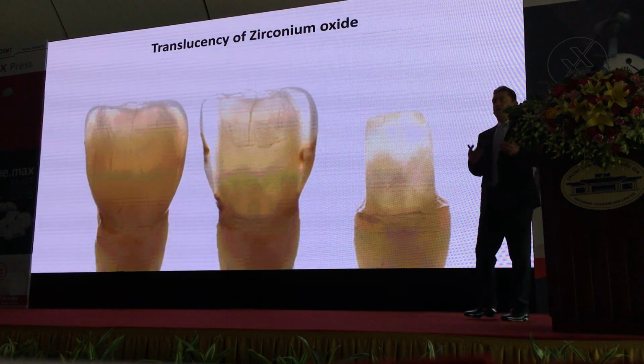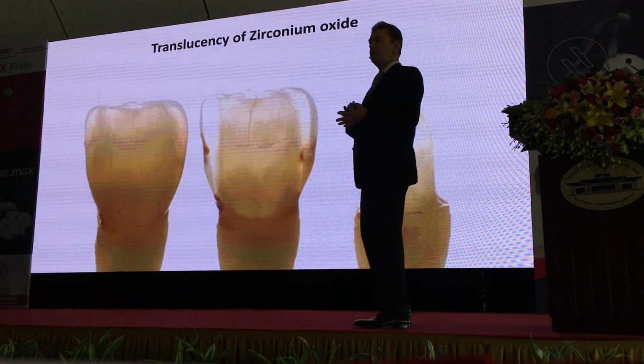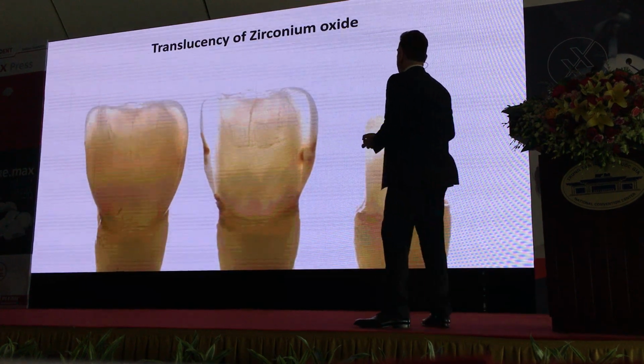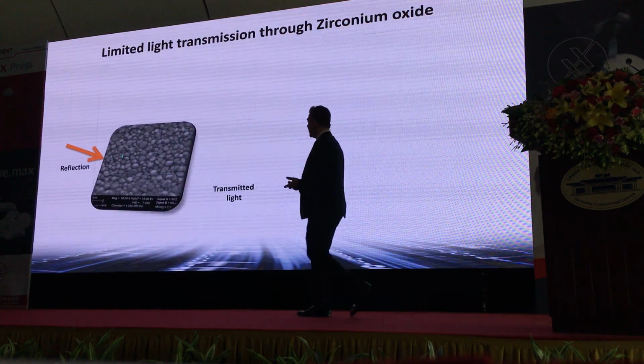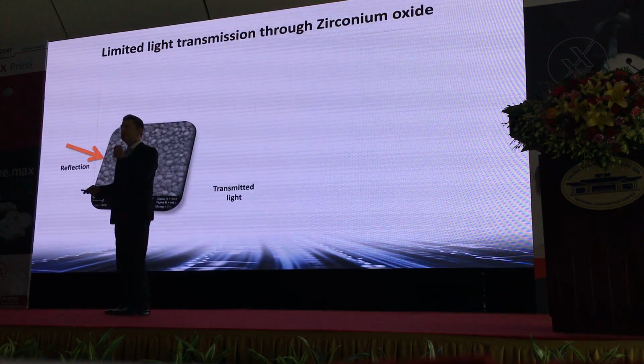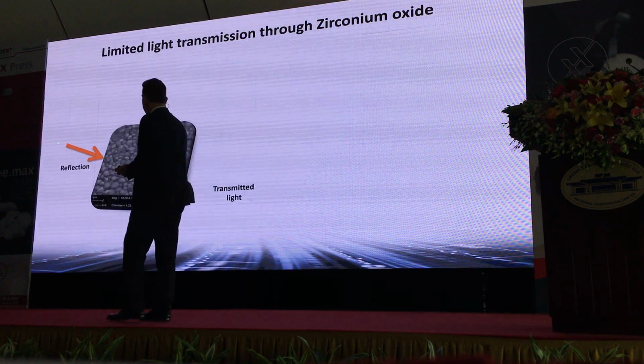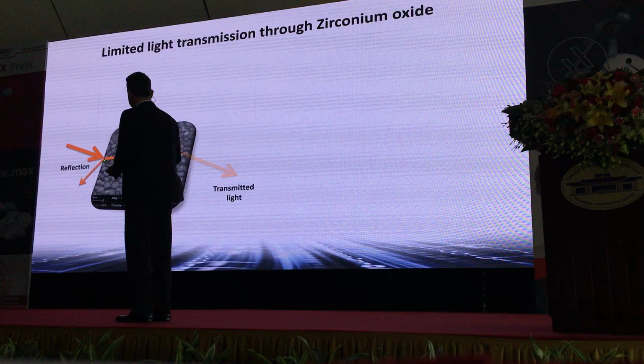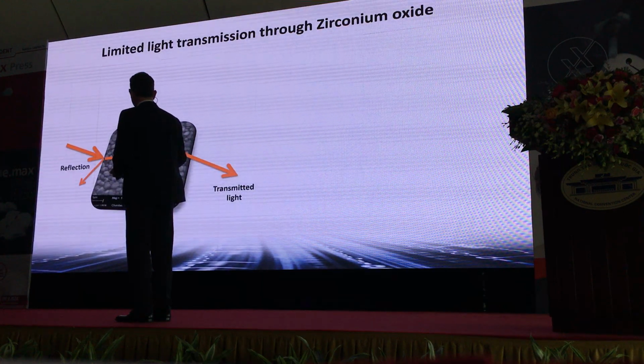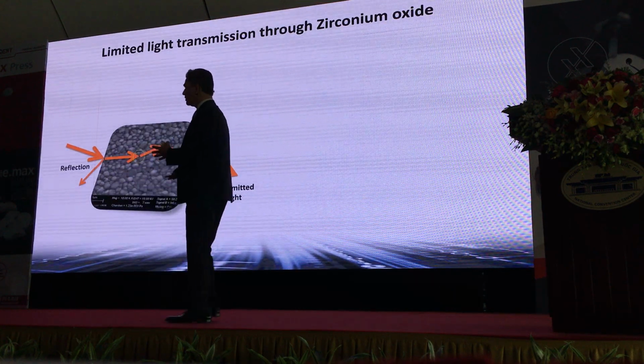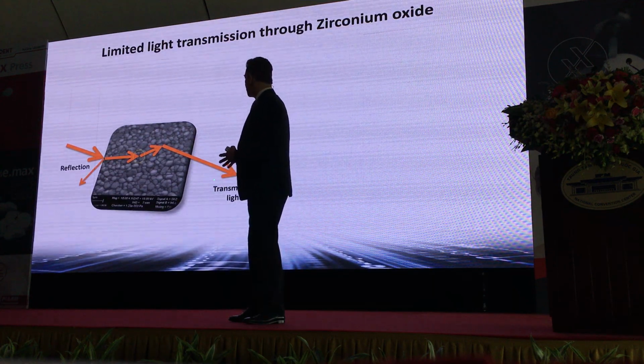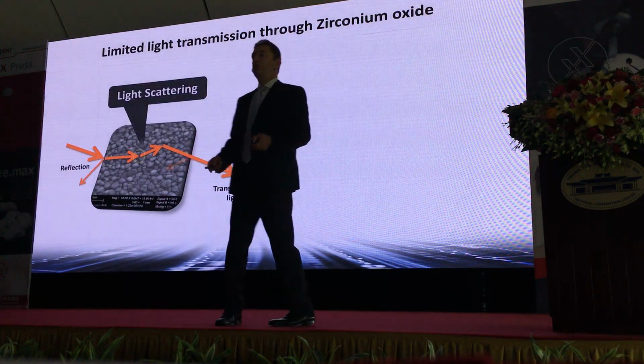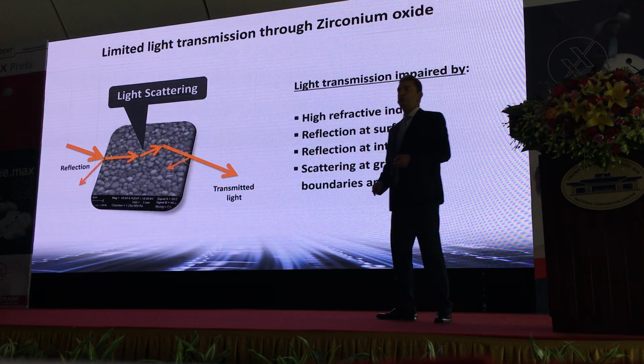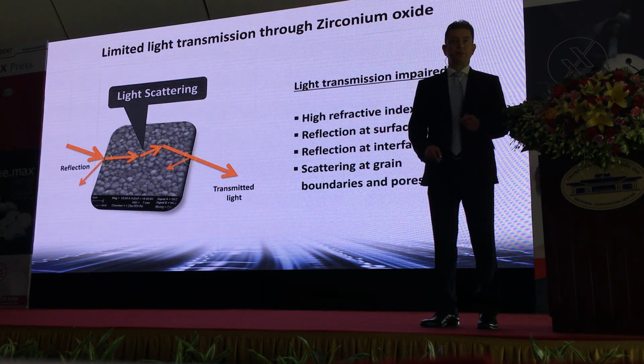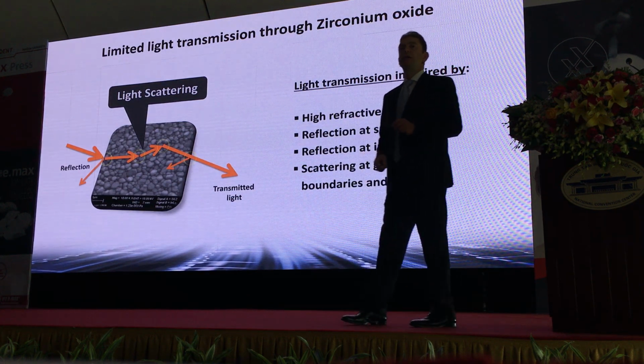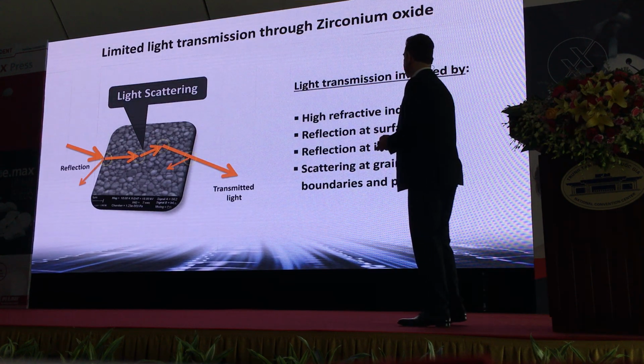The problem is now with aesthetics, right? It's always the same thing. Strength and aesthetics. Sometimes difficult to balance. So the zirconia ceramic, you know, we don't have a glassy matrix with the zirconia. We have only polycrystals, no glassy matrix. And you can see when the light goes into the material, some of it will be reflected, but inside the material, on these grain boundaries, the light is refracted many times. So we don't have so much light going through the material. And this is why usually zirconia looks much more opaque compared to glass ceramics where we have a glassy matrix. Okay? So one of the shortcomings of zirconia is that it is more opaque compared to glass ceramics.